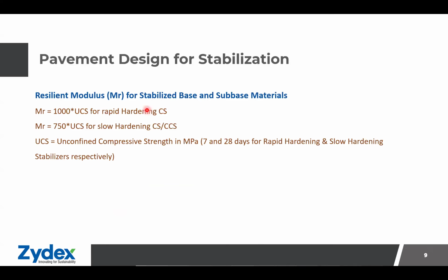We need to give the 3 inputs to the IITPAVE for each layer. That includes the resilient modulus, its Poisson ratio, and its trial thickness. Based on that, we can do the stress strain analysis, and then using the distress functions, we can find out the adequate pavement layer thickness. So the guidelines suggest the resilient modulus depending upon what type of hardening chemical stabilizers we are using.